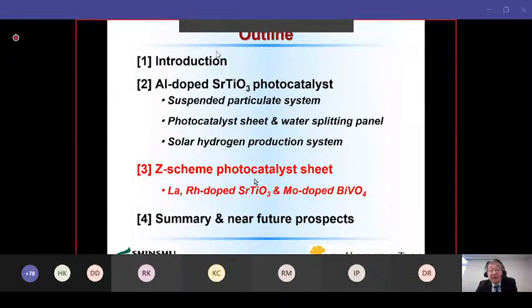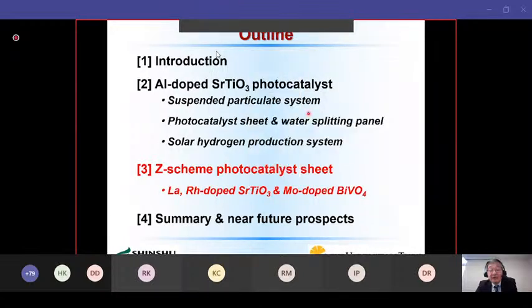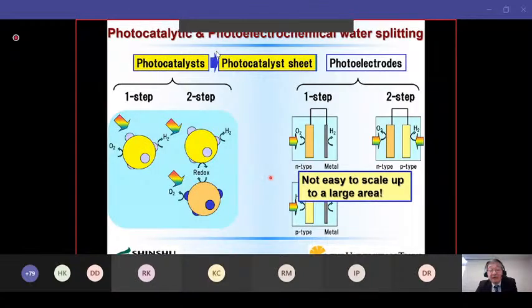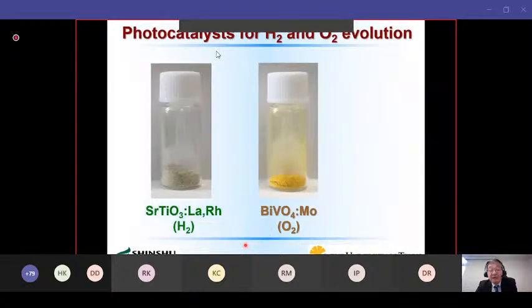Now let me move to a slightly different type of system. This scheme is the photocatalyst sheet. In this case, we use two different types of photocatalyst, and I will talk about this so-called Z-scheme water splitting system. This is lanthanum rhodium co-doped strontium titanate for hydrogen evolution. This is molybdenum doped bismuth vanadate for O2 evolution.